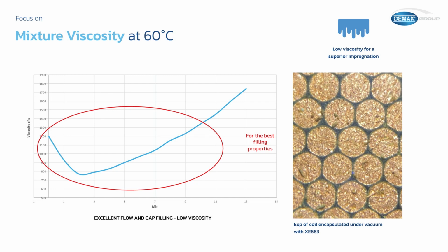Here you see the mixture viscosity at 60 degrees that remains very low for a good long time, sufficient to wet perfectly the wire. You see a section of the wire where no air is present between the different windings. So it's very important that the resin without air can show the maximum heat dissipation that it can show.